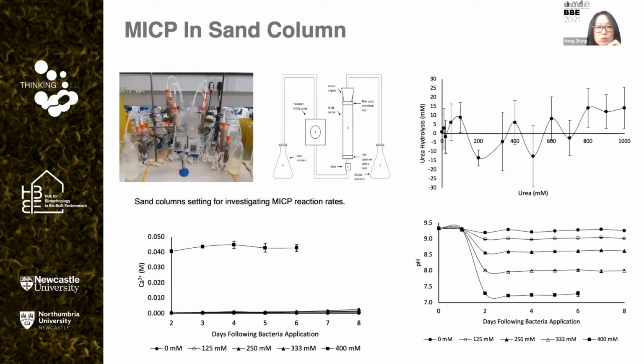Jamie also tried to investigate the urease activity in sand columns. The image on the left shows the lab settings and the scheme for the sand column experiments. However, it turned out that it's very difficult to measure the urea hydrolysis and the amount of ammonia being produced in the sand column, as we can show in the top right figure. But Jamie found that when the calcium ion and urea have a 1-to-1 ratio in the reactant solutions, the utilization of the calcium ions was the most effective condition.